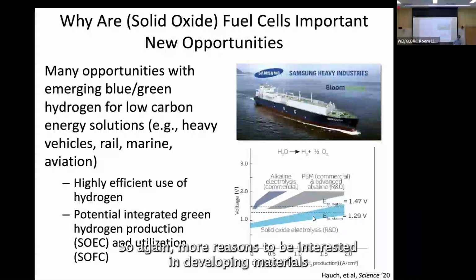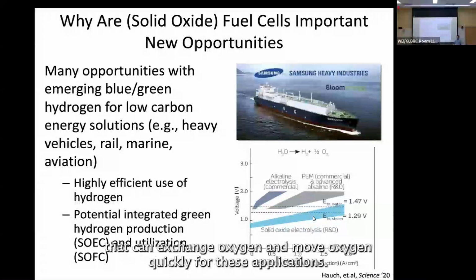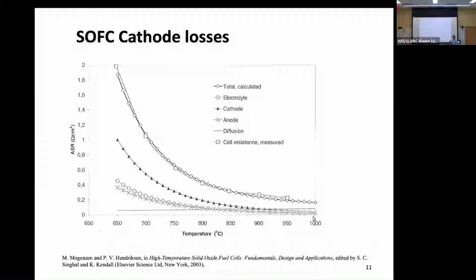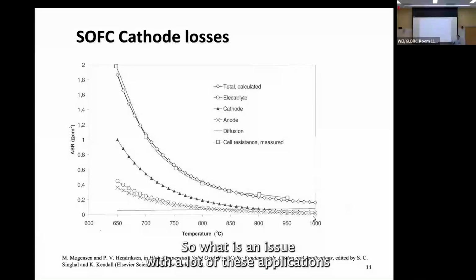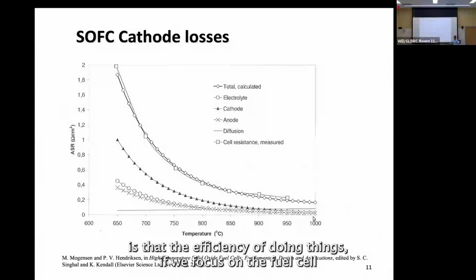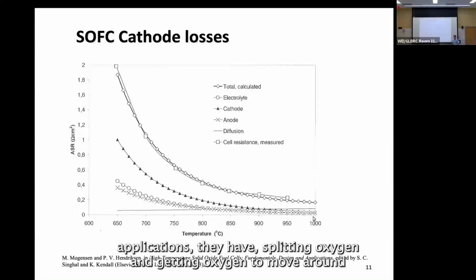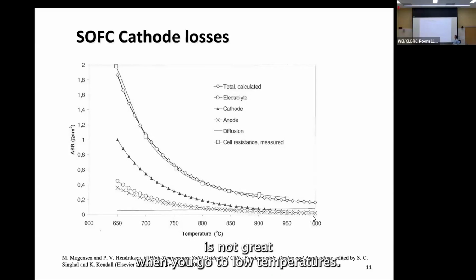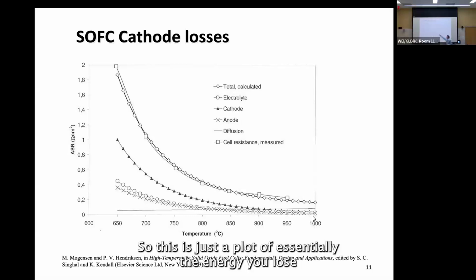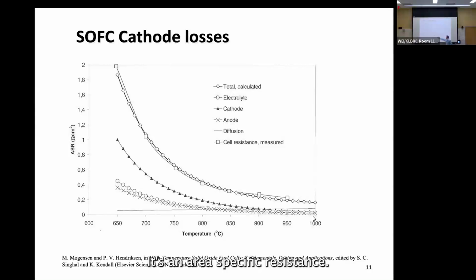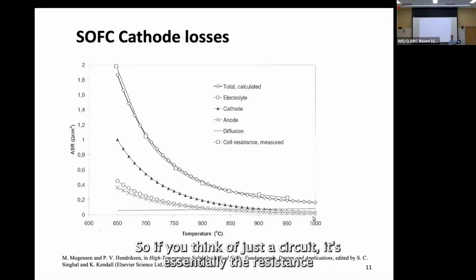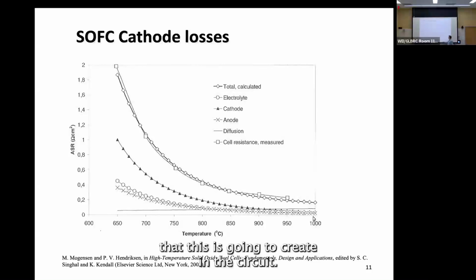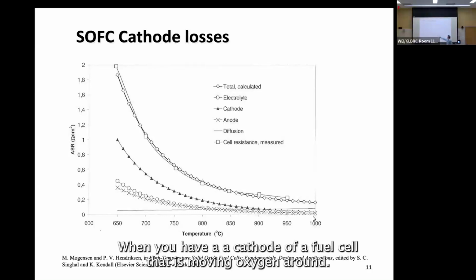So again, more reasons to be interested in developing materials that can exchange oxygen and move oxygen quickly for these applications. So what is an issue with a lot of these applications is that the efficiency of doing things, if we focus on the fuel cell application, say of splitting oxygen and getting oxygen to move around, is not great when you go to low temperatures. So this is just a plot of essentially the energy you lose when you split an oxygen and use it in a fuel cell. It's area-specific resistance. So if you think of just a circuit, it's essentially the resistance that this is going to create in the circuit when you have a cathode of a fuel cell that is moving oxygen around.